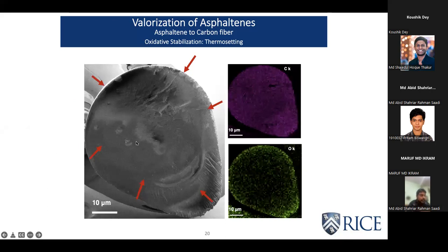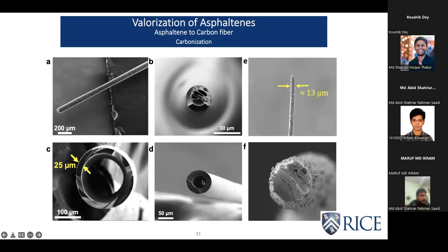This is another proof: we did SEM and EDAX, which is energy dispersive X-ray spectroscopy, which basically gives elemental composition. So this is the fiber cross section. And as you can see, the carbon is uniform throughout, but oxygen is mostly present on the surface. In the core, oxygen is not there, which suggests that only the surface regions have been oxidized, whereas the inner core has not been oxidized properly. And I'll show you the consequences. So this is the consequence.